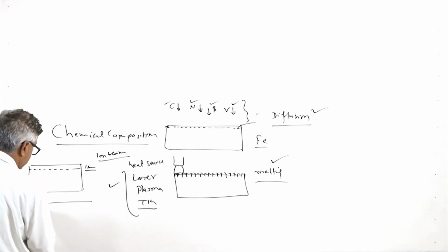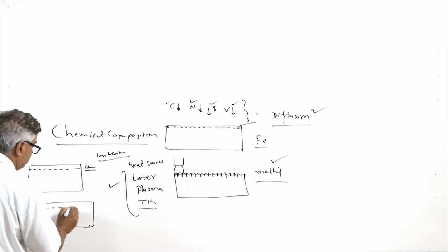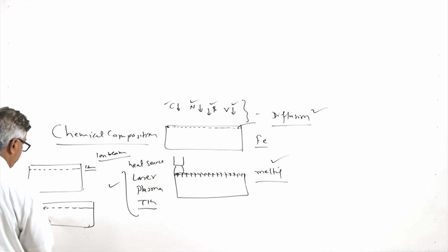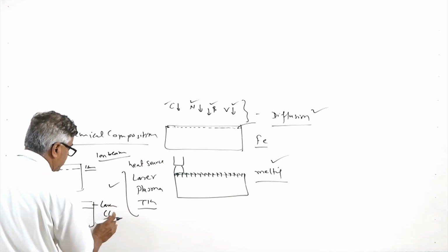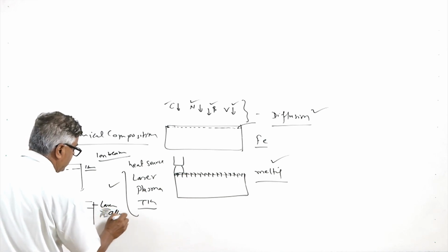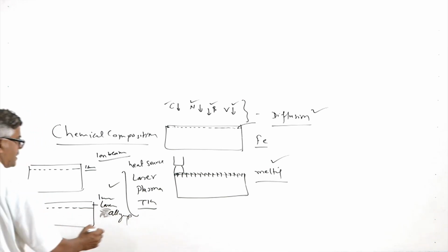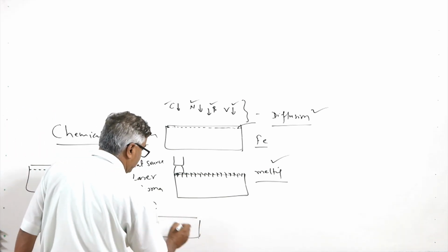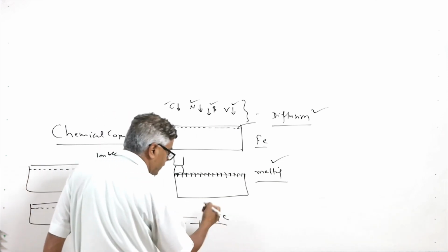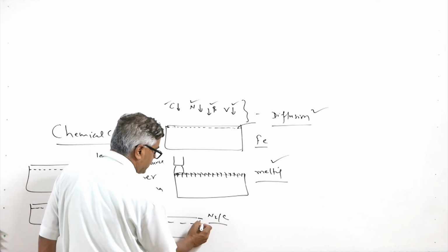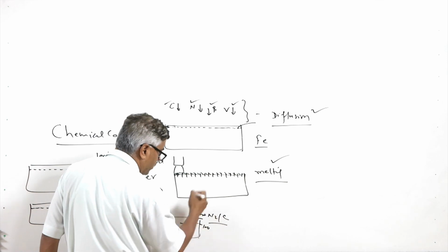While in other cases the depth which is modified, like in laser cladding, laser alloying or TIG alloying, this depth may be even 1 mm or so, while in other cases where nitrogen and carbon are introduced at the surface in carburizing and nitriding methods, this depth may be like say from 100 micron to 1000 micrometer or even more.